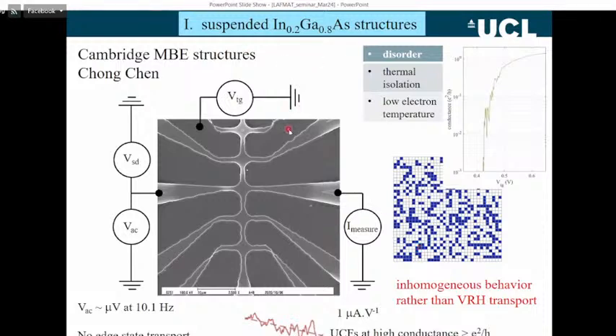So this is a typical structure. It's freestanding. It's an SEM image. The scale bar there is 10 microns, so it's not the smallest structure. It's a few microns across. You can see we've etched away underneath. Some of the etch has come through and destroyed the device. Where it's etched through, we just get a small pillar underneath that holds up the system.